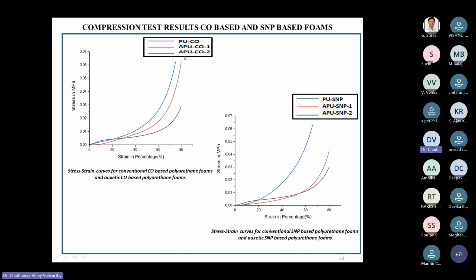Next, these are the CO based and SNP based PU foams. The same trend is going on in these compression test results. There is no linear elastic region and no yield point. We cannot know exactly where the yield point is, but from previous studies, when the curve turns towards densification, they consider that point as the yield point, which is not clear until now, because hyperelasticity is completely a non-linear effect. So we can't map the yield point exactly for these foams. But for normal foam, we can know the yield point to a certain level, which is the end of the linear elastic region.